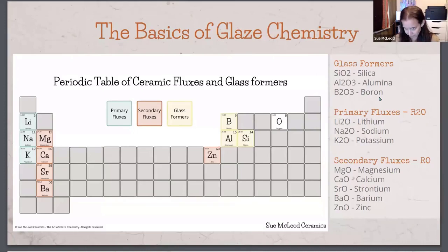And then alumina is the material that prevents the glaze from running onto the kiln shelf. It can be called a stiffener. What it does is it increases the melted viscosity of the glaze. So viscosity refers to the physical thickness of a liquid. So when our glazes melt in the kiln, the liquid that they form can either be thick, high viscosity, or very thin like water, low viscosity, and that's when you get running. So the more alumina you have in your glaze, the higher the melted viscosity during the firing, and the less chance your glaze is going to run.